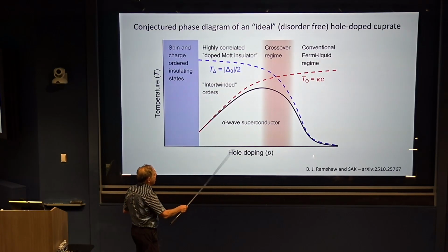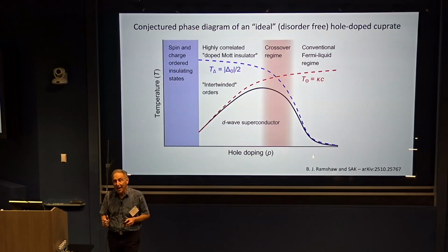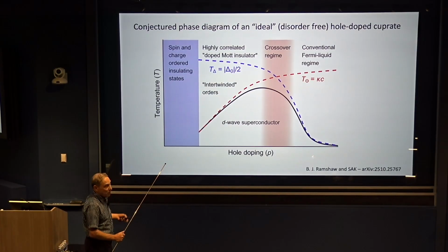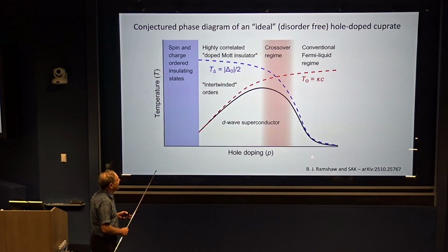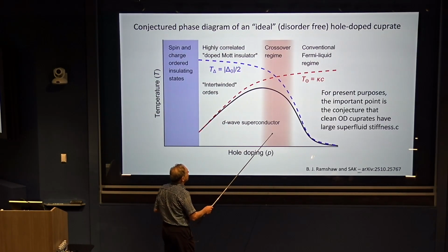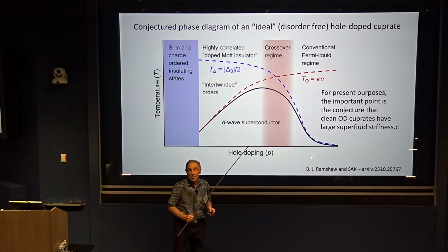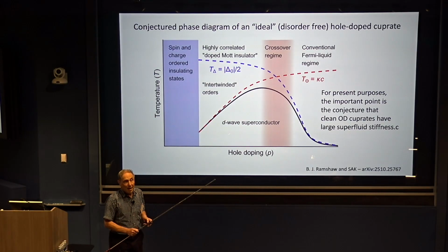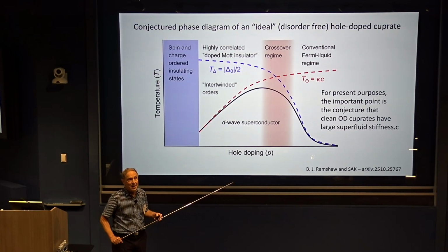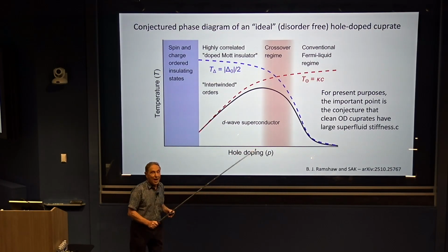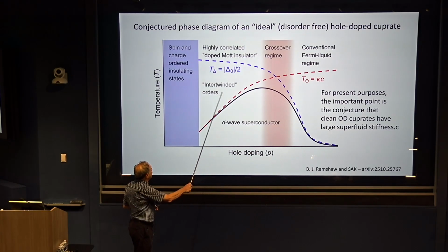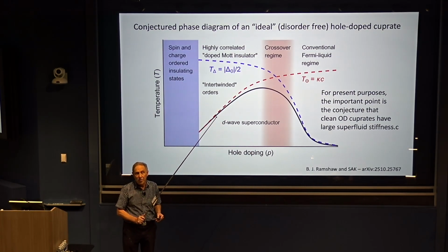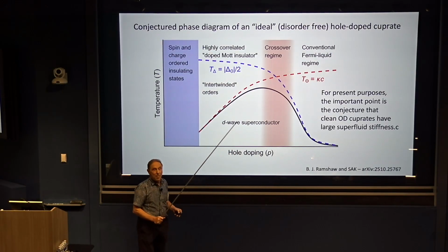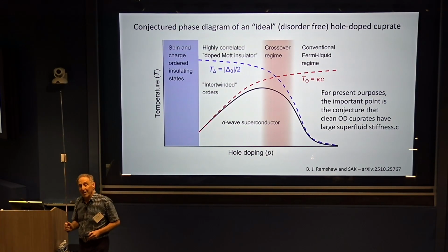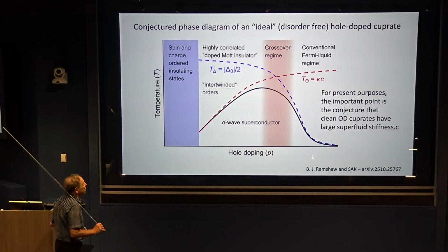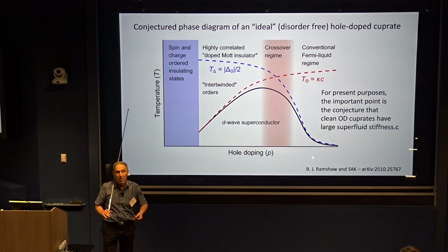And there are many things about this. If there's time in the discussion, I would be happy to tell you the motivations behind this and some of the implications. But for present purposes, the only thing that I want you to take away from this is that there is reason to at least conjecture that the original idea that TC is bounded by phase ordering on the underdoped side, but is bounded by pairing on the overdoped side, and that the superfluid density on the overdoped side is intrinsically large. That's what I'm going to assume from now on.